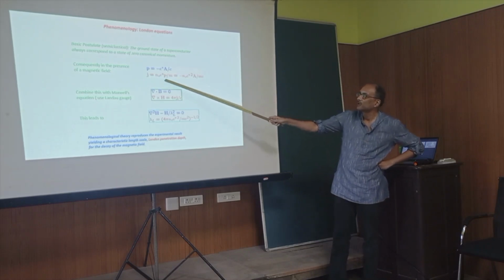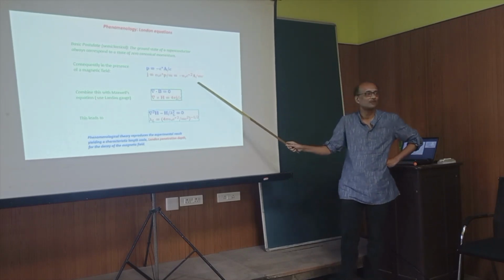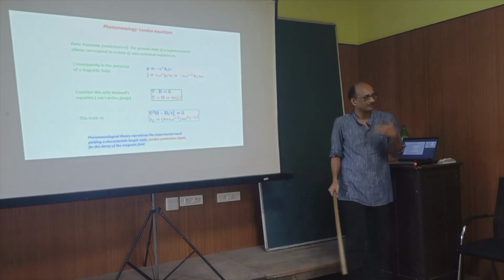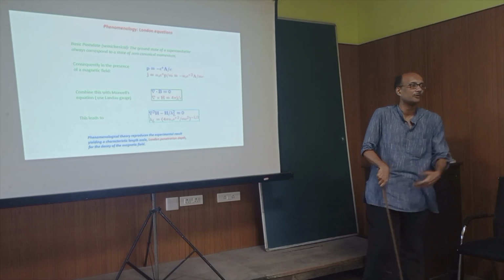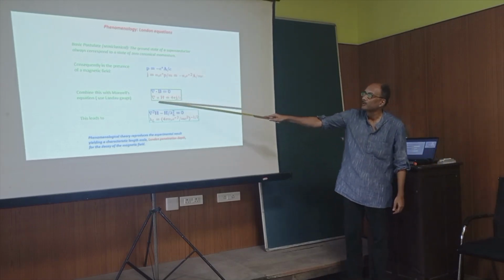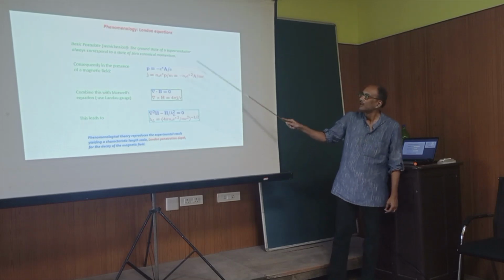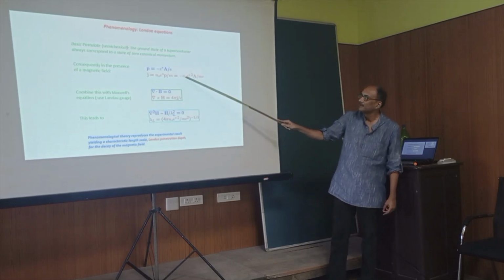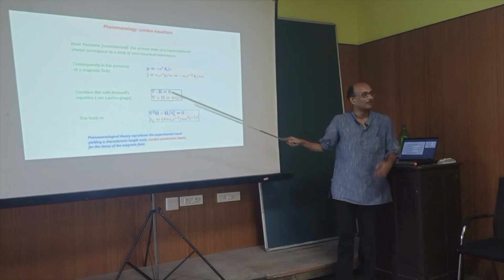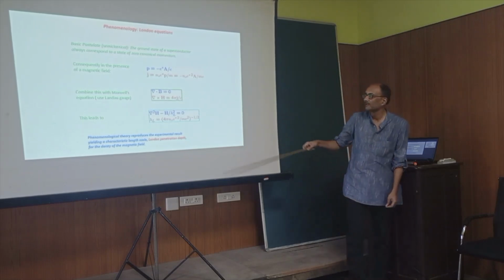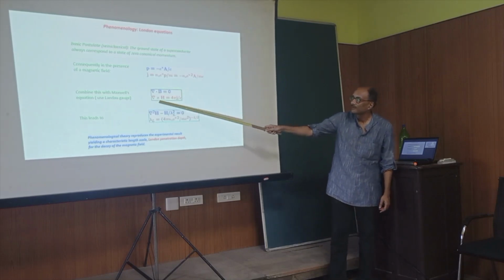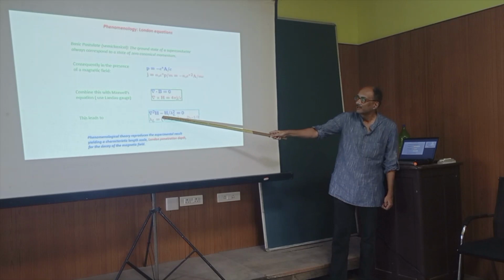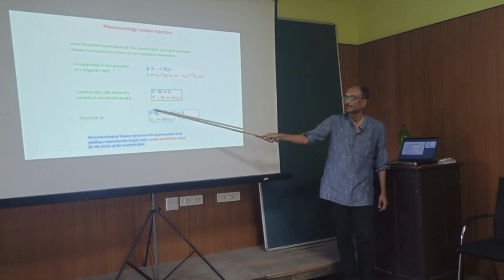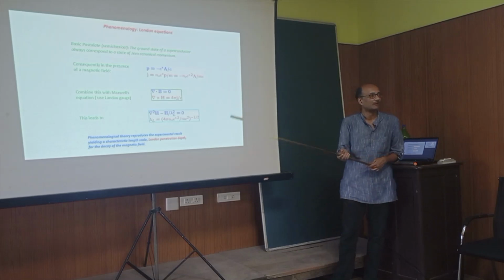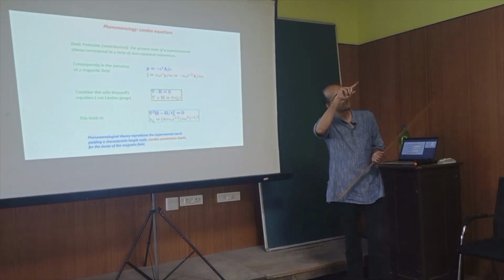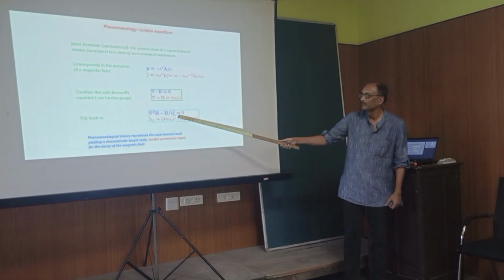And if you just put in this expression of P, you find that the current is proportional to the vector potential that you have put in. So the vector potential is there because you have put in a magnetic field, and that's how you are looking at it. So you take this and you put this in the Maxwell's equation. Okay? Once you do that, you immediately see that because there is an A here and H can be written as curl of A, if you simplify this equation a little bit, you immediately see that the equation for H essentially is such that this is an exponentially decaying pattern. So this is a standard equation which can be solved by putting in H equal to exponential of minus x over lambda, and this lambda is the penetration depth.